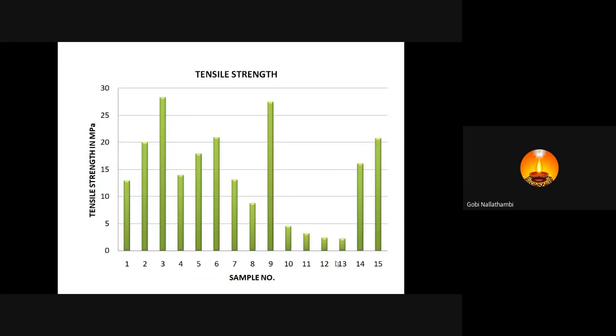While comparing the tensile strength of the samples, the tensile strength in terms of megapascal, that is MPa, sample 3 is giving the highest value. Next one is sample 9. If you look at sample 11, it's very poor. So when we compare the proportions, we can say why samples 11 and 12 are very low.